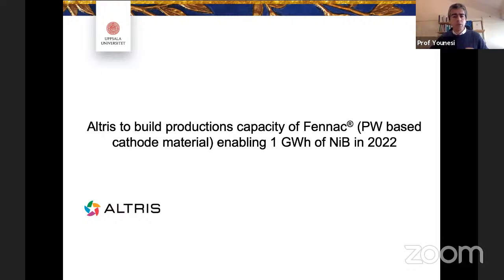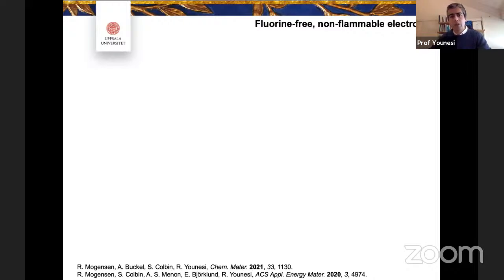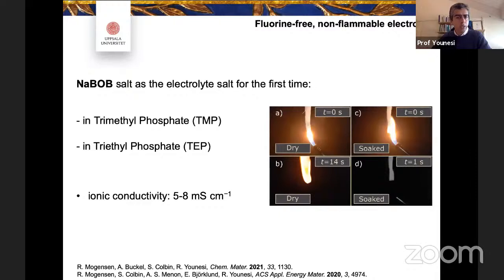This is one example of material which has been studied in my team. The other one is electrolyte related, which we have been focusing a lot on developing fluorine-free, non-flammable electrolyte. And for the first time, we show that NaBOB can be used actually as electrolyte salt in sodium-ion batteries. And in a few recent studies, we have shown that NaBOB can be used in TMP, TEP, and other phosphate solvents with relatively good ionic conductivity in the range of 5 to 8 millisiemens per centimeter, and makes the electrolyte non-flammable, which is another advantage for the sodium-ion batteries that we are developing, to have such fluorine-free and non-flammable electrolytes.